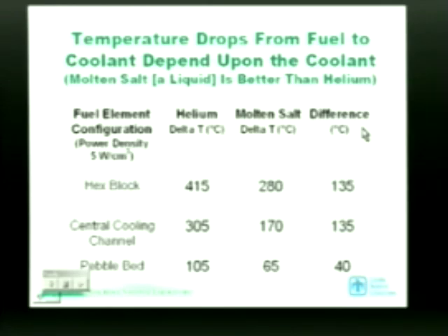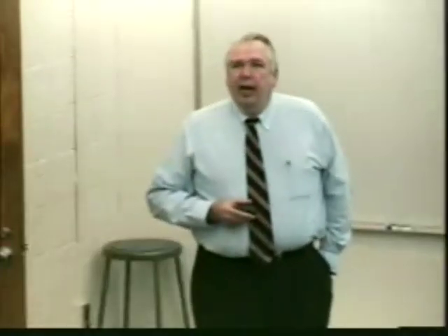I'd now like to discuss the fuel and the implications of the fuel and using a liquid coolant. I make the following observation. The temperature drop between a fuel and a coolant depends upon the fuel design and the coolant. In the next slide, I'm going to show you some numbers. I'd like to first point out, though, that if you're building a graphite reactor, you can make several kinds of fuel. You can make hexagonal blocks. You can make it in a form of a central cooling channel where you have an annular fuel zone with a cooling channel in the middle, or you can have pebble bed reactors, where the reactor has microspheres in a ball of graphite about the size of my fist, and you just fill up the whole reactor with these fist-sized balls until it's completely full. Many different fuel designs, but the same basic concept, microspheres embedded in graphite.